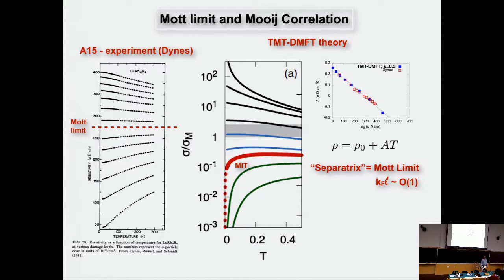At the risk of making this more baroque or completely rococo, can you also understand how this phase diagram works together with a superconductor-insulator transition? So if you use the same phonons to make pairs... I think literally speaking, we could extend this theory to introduce pairing. Whether this will capture all the interesting effects of the interplay of disorder and superconductivity, I'm not really sure about, because we've seen from beautiful work that Amit showed us and earlier work by Nandini and her group that,